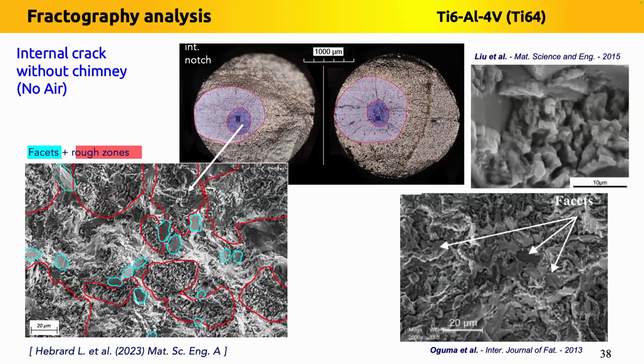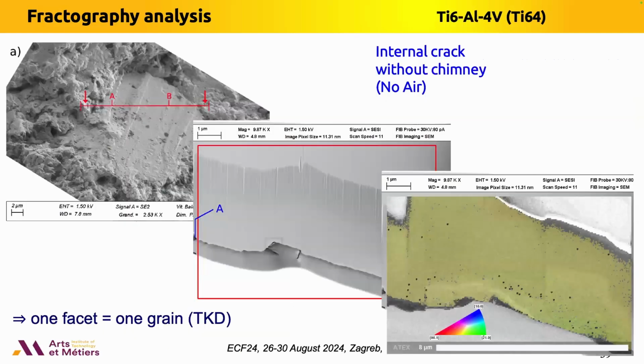And if we want to know what happened in the facet, why there is this facet, we have cut it by FIB and observed it. We observe that there is a unique grain, observed by transmission Kikuchi diffraction, so probably this grain was broken by a cleavage or quasi-cleavage.